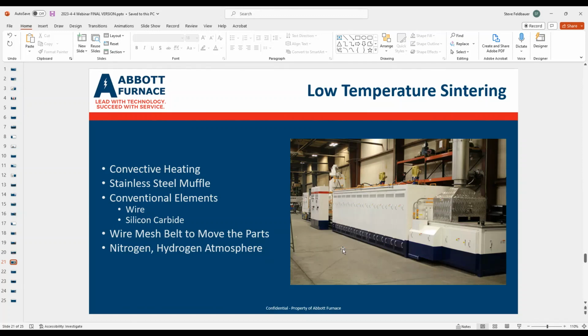That's really important then, because in the case of a vacuum, you don't have the advantage of that convective heating. It's truly a radiating heating package, and so to get the control, we already see the variability even at the high temperatures. At these lower temperatures, your variability goes up much more. And so that's why it's so important for you to have convective heating. In this case, we would have a stainless steel muffle that goes down through. It's all wire wound elements. Or it could be silicon carbide, whichever you choose.